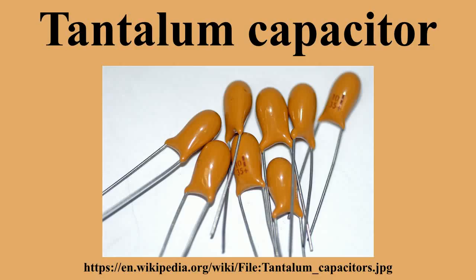More than 90% of today's rare failures in tantalum solid-state electrolytic capacitors are caused by shorts or increased leakage current due to this failure mode. The extremely thin oxide film of a tantalum electrolytic capacitor, the dielectric layer, must be formed in an amorphous structure. Changing the amorphous structure into a crystallized structure is reported to increase the conductivity by 1,000 times, combined with an enlargement of the oxide volume.